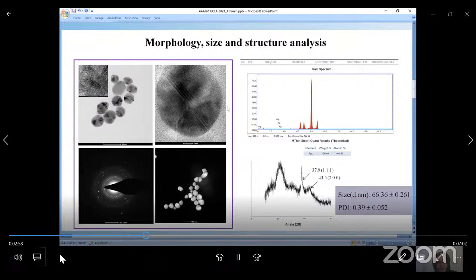Transmission electron microscopic analysis was carried out, which shows the metallic fringes confirming that the silver formed is of metallic nature, and the diffraction images confirm that it is of monocrystalline nature. Further, the spectra also confirmed that these particles are silver, and the XRD showed a sharp peak of crystalline nature. The dynamic light scattering showed the size to be nearly around 66 nanometer, and the polydispersity index to be as low as 0.39.